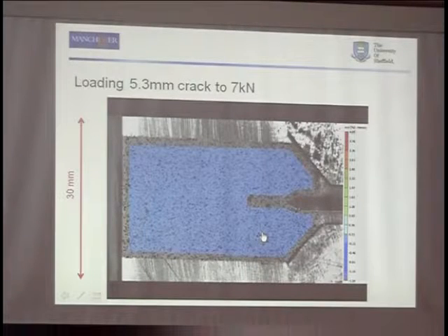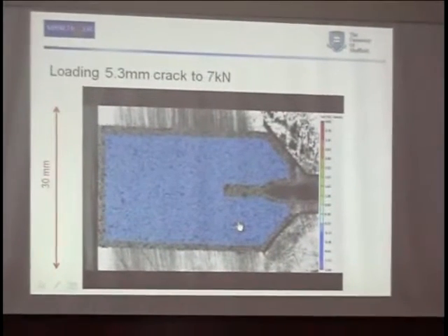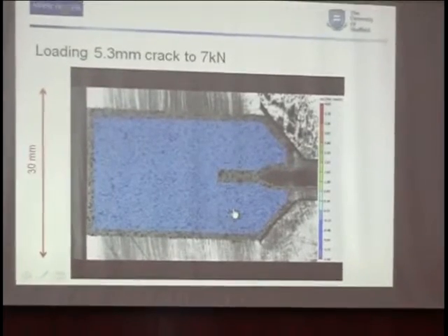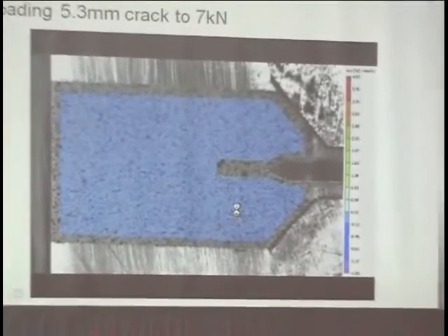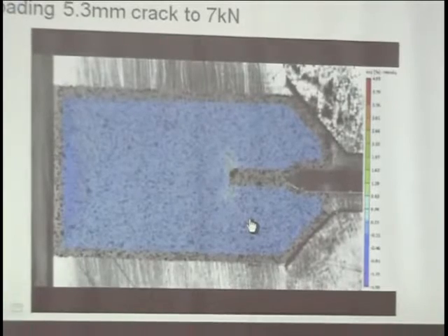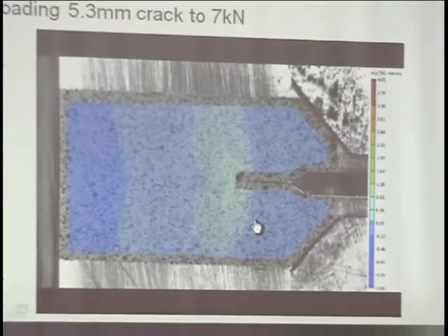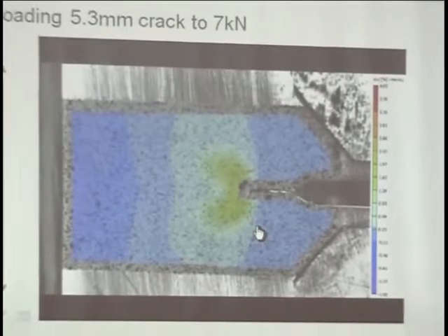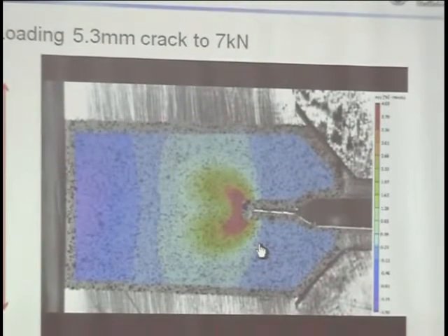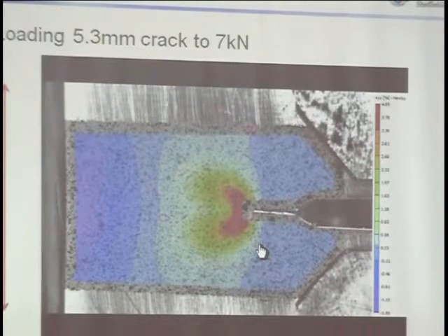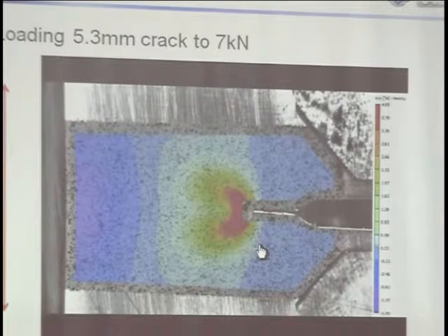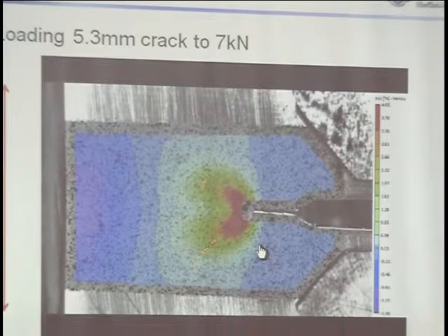This is just a video of the macro fields. What it's showing you is the strains in the y direction during a tearing test. This is at the 5.3mm crack, once we started tearing. You can see that it's quite characteristic of the strain fields for a CT specimen, the double lobes, and strains of up to 4%, but this has gone way past the fatigue crack loads.